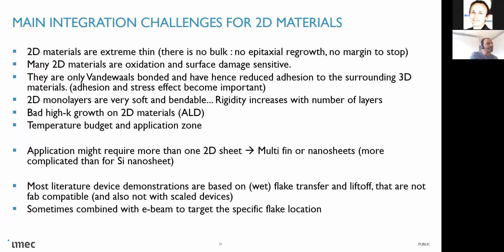because the material performance will also be dependent on the control and the strain variation that you put in the material. If you increase the number of layers, we see that the rigidity of the stack increases very fast, and this is maybe something that we will need to consider later on. And the other thing is that it's a self-passivated material, so the growth, the nucleation of chemical vapor deposition, or ALD, is also very challenging and very irregular.